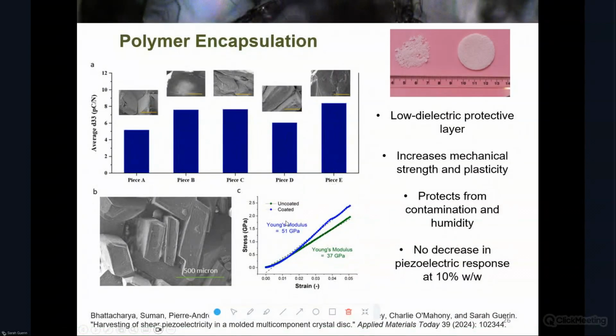So if you put one of those co-crystal discs, I think this is actually glycine again, into your beaker of water, after about 10 minutes, this is all that's going to be left of it. But when we coat our crystal assemblies in our low dielectric polymer, low dielectric so that we don't decrease the piezoelectric response, you can see that it lasts for as long as it needs to in those high humidity or literally submerged in water applications. So that was great work done by Tara to achieve this, again, protocol for this workflow of molecular crystal piezoelectric devices.